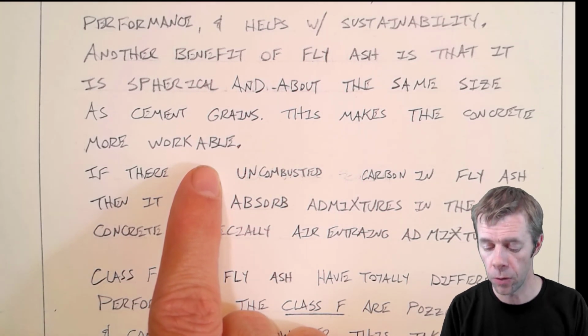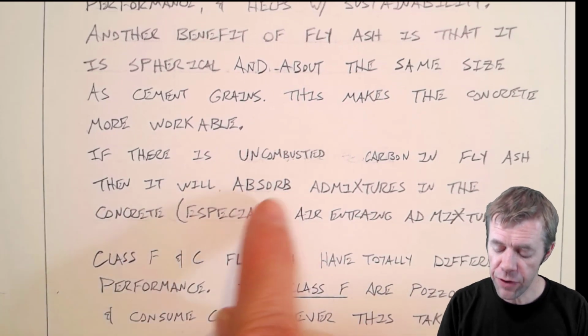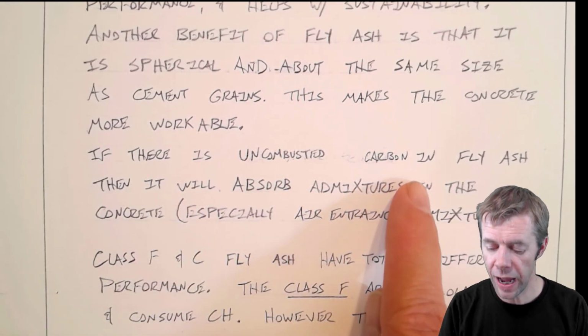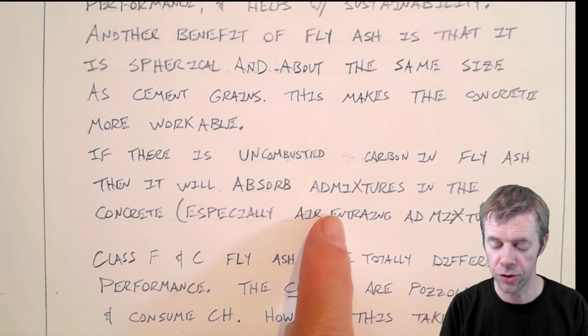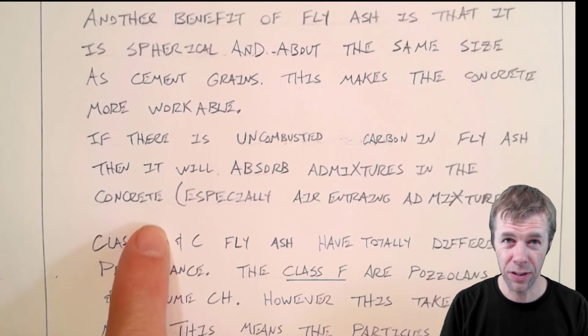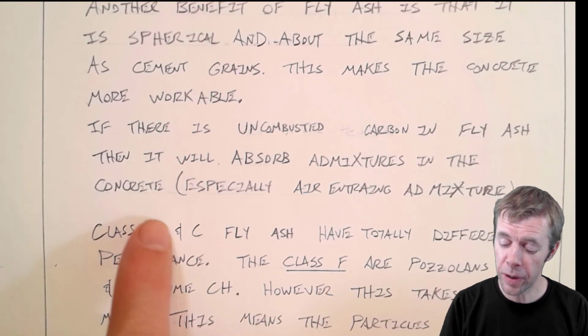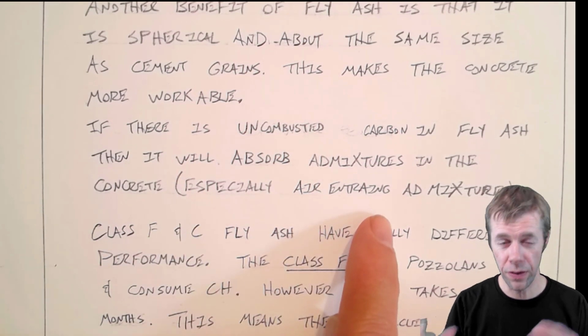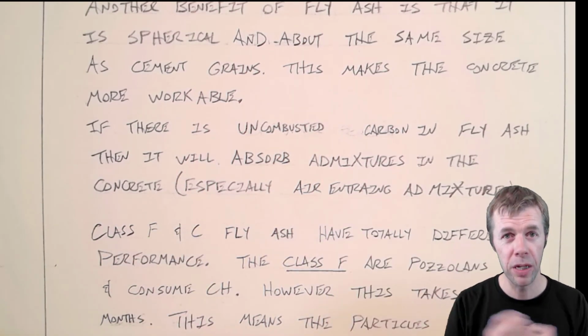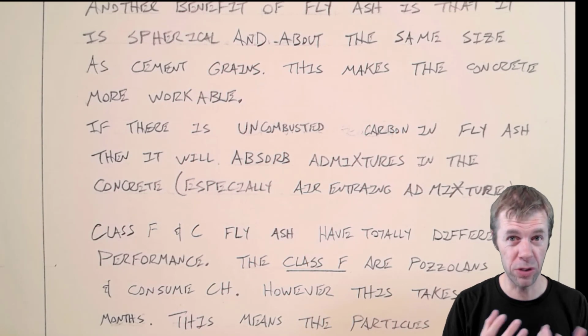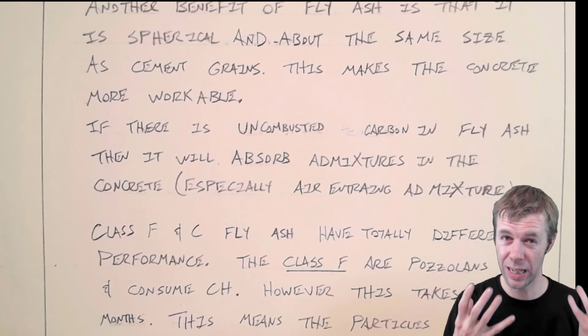lower water cement ratio. And if there's uncombusted carbon in the fly ash, then it will absorb the admixtures in the concrete. Yeah, that's not good, right? Especially if you have air entraining admixtures, then this carbon will just suck it all up. And it won't make it available to stabilize the bubbles. That's not good either.